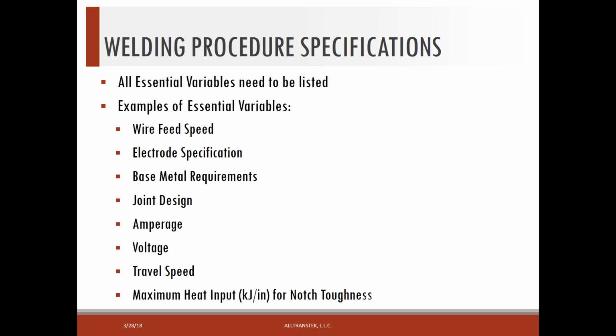Okay, welding procedures. Now we've got a PQR established and we have to do a welding procedure. We have to list obviously all the essential variables, and these are some examples: wire feed speed, your electrode specification, the base metal limitations, and that gets back to M numbers, P numbers, and group numbers, what kinds of joints will be used, amperage and voltage specified as a range, and travel speed also. And then for notch toughness, what was the maximum heat input that was used to qualify the procedure.